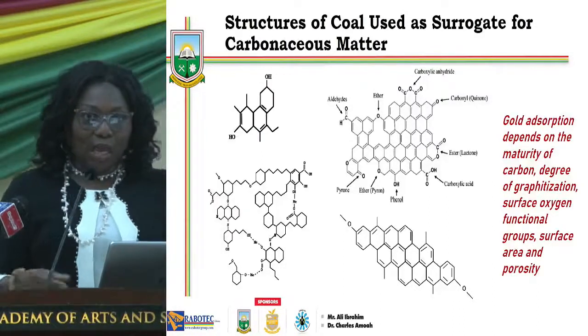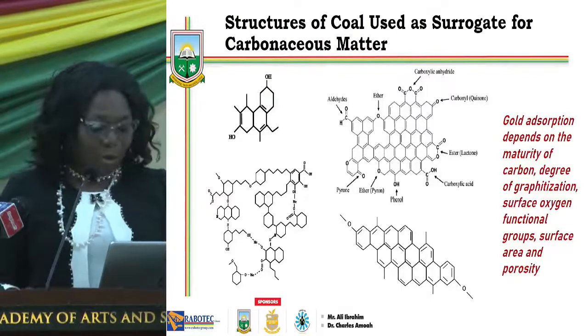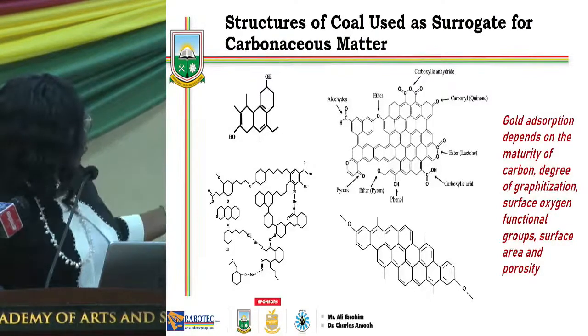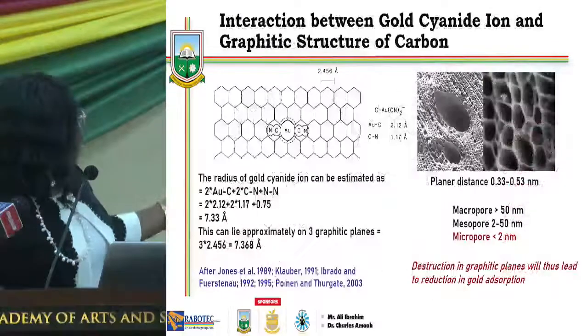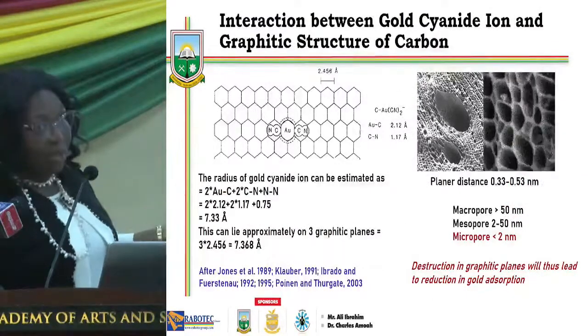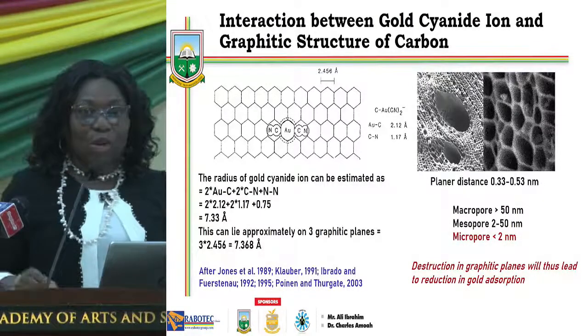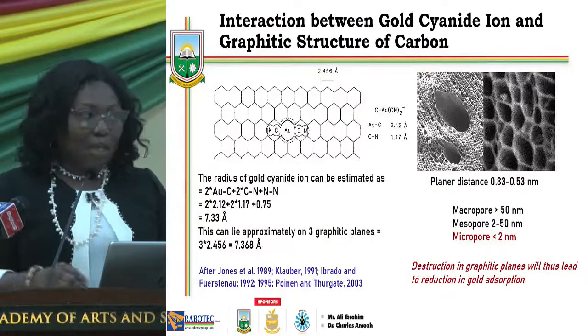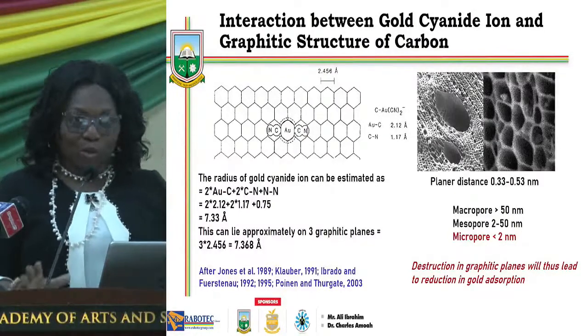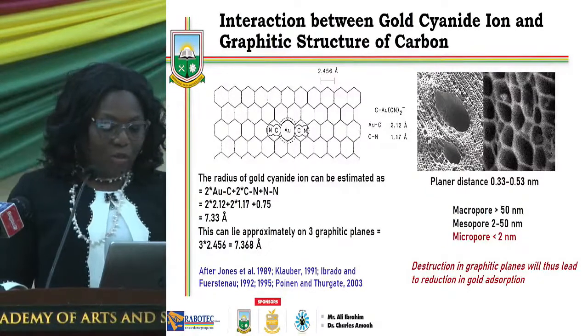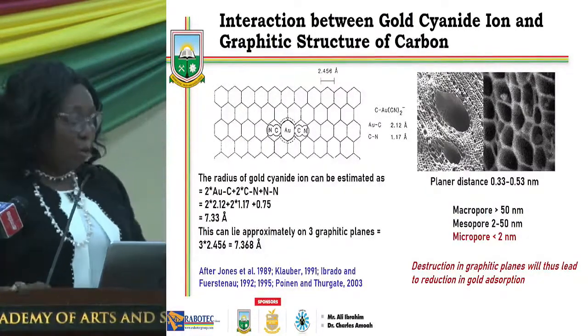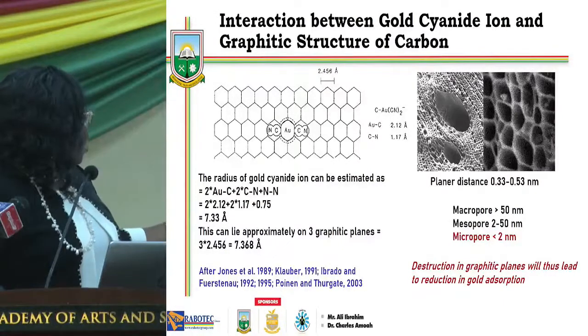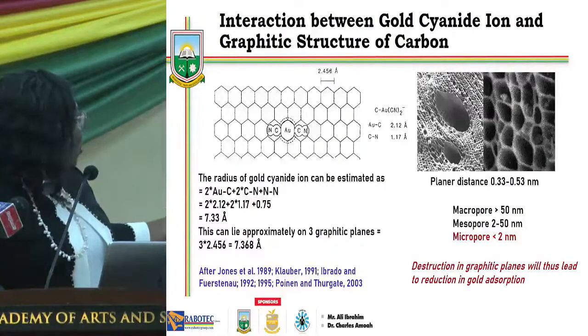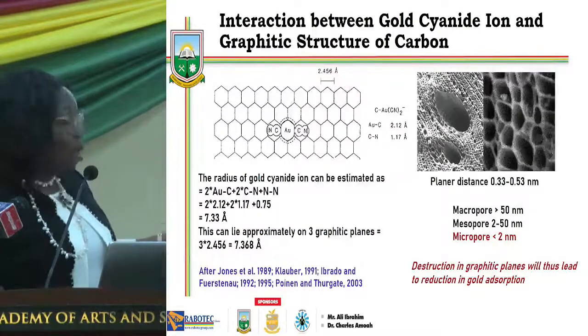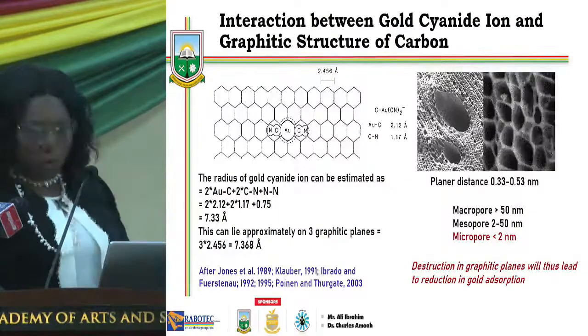So people have studied how gold adsorbs, and some researchers have come up with this diagram here, which shows that the gold cyanide ion will lie on 3 of the rings. What does it mean? It means that when there's a break in the rings, it's going to affect gold adsorption. And then I also spoke about the porosity or the surface area. So if we look at the pores within the carbon, we have macropores, the bigger pores, mesopores, and the micropores. And research shows that the most important pore is the micropores.